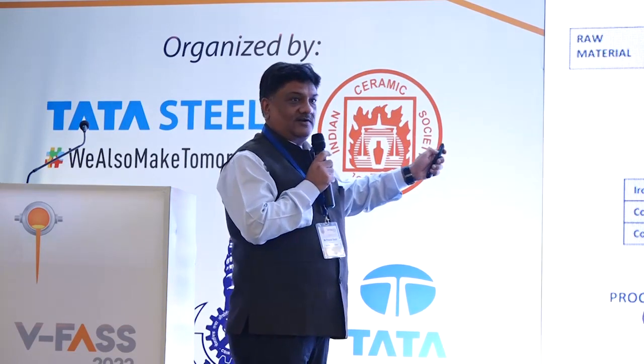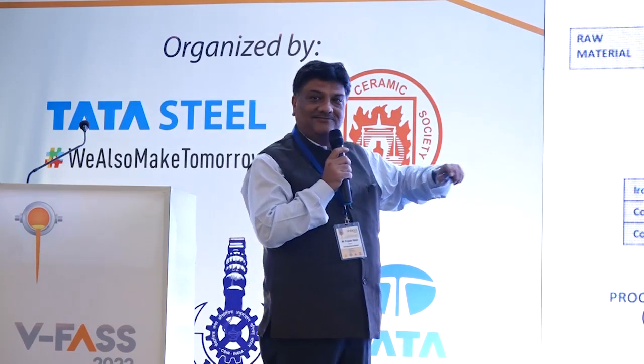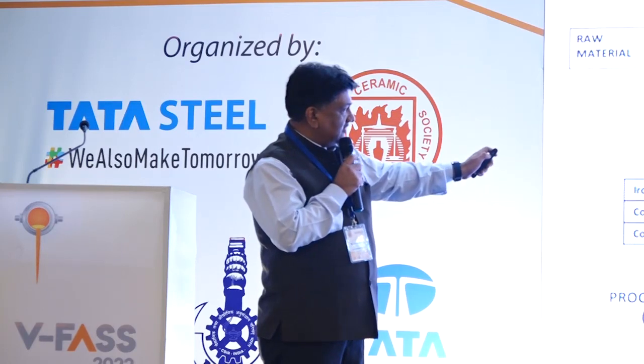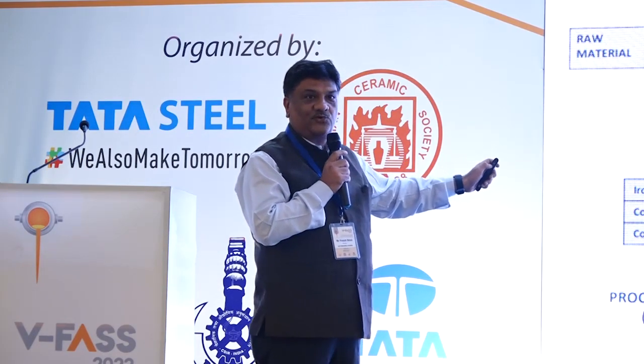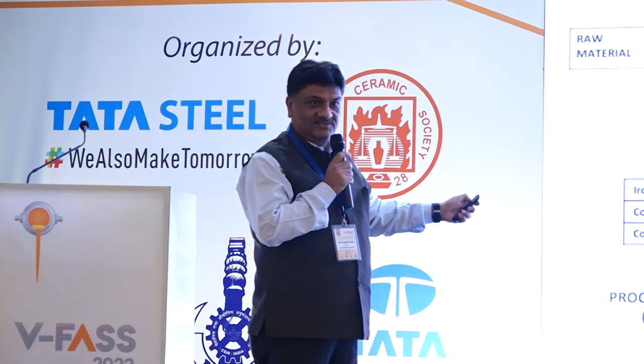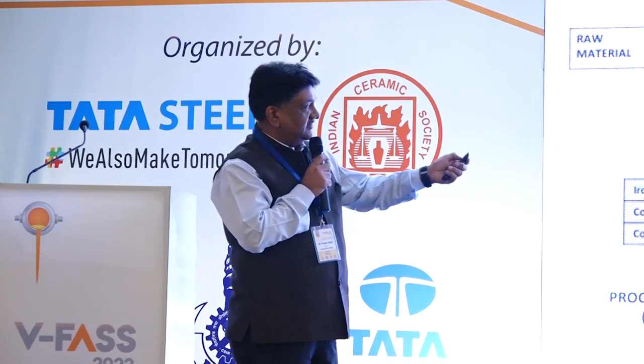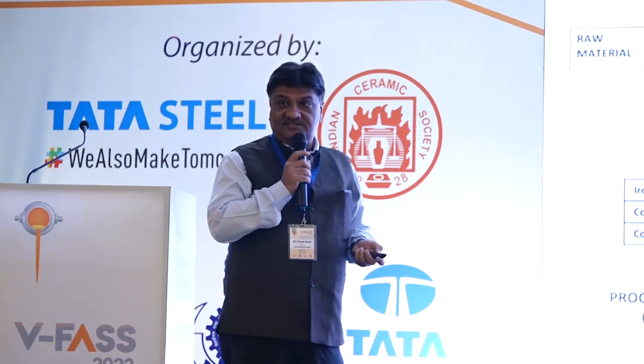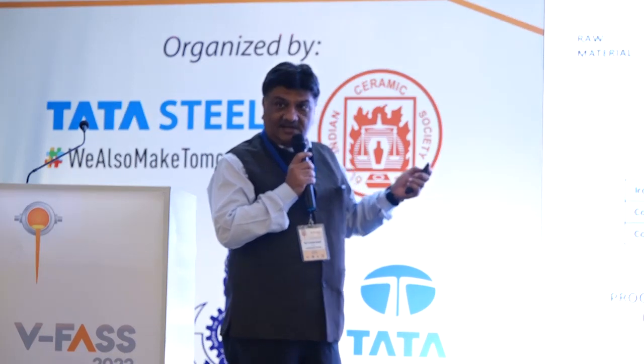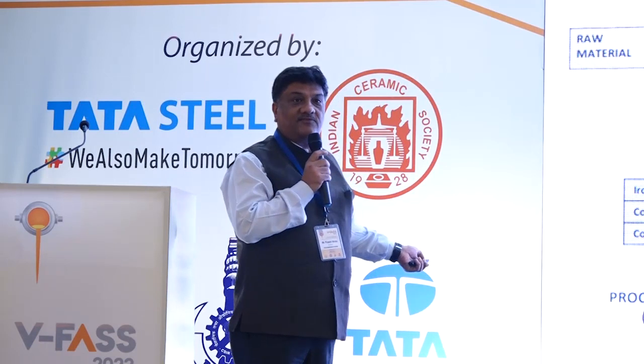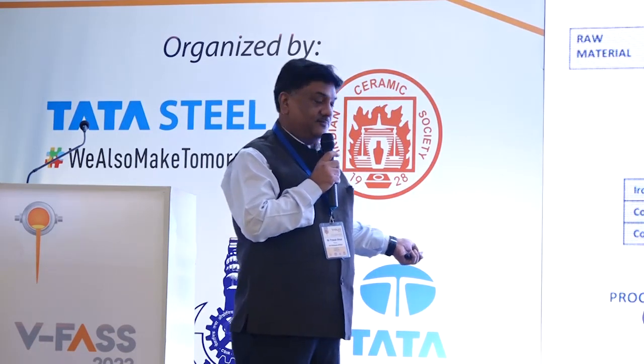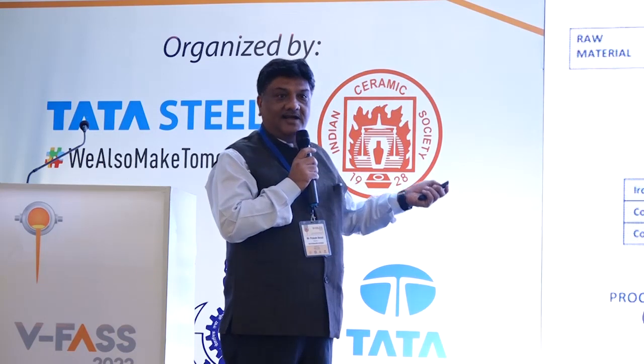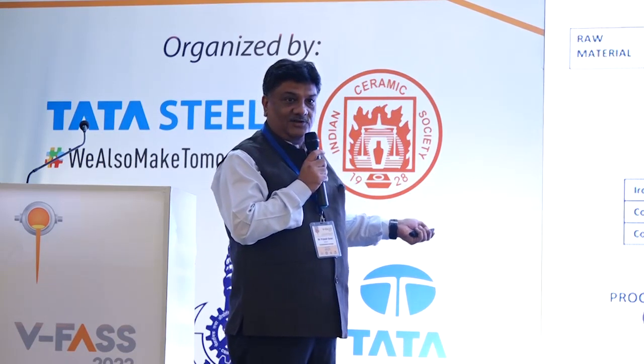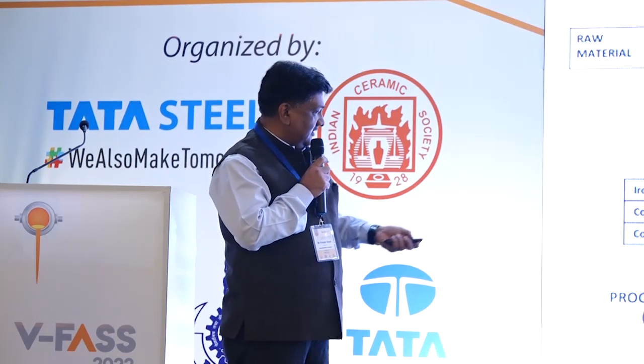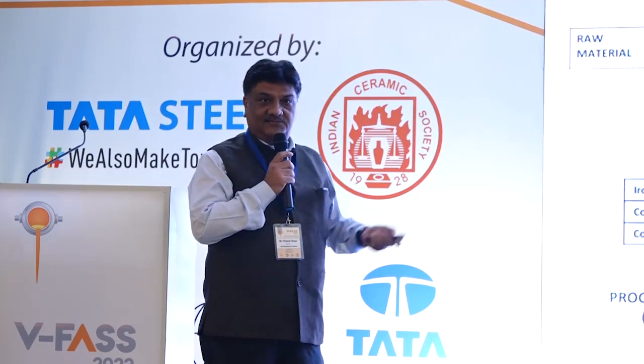But what is the scenario? The statistics have been done, and the numbers vary. Around blast furnace slag, we have 24 million ton per annum, 24 to 27 as Dr. Mohapatra has also mentioned. But the LD slag is around 12 million ton. So these are the statistics. The alarming situation is that by 2030, the BF slag will be available at 40 to 50 million ton per annum. And the LD slag again will be increasing by 10 to 15%, 15 to 20 million ton per annum, and of course the LF slag.